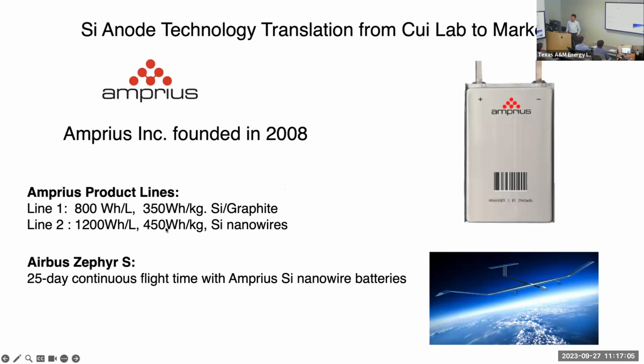Amprius is now delivering 450 watt-hours per kilogram product to the market, and we also have a silicon particle line that delivers 350 watt-hours per kilo. This is much higher energy density compared to the existing graphite technology. One of our high energy density batteries, we supply to Airbus, the Zephyr S, a commercial drone flying at very high elevation, about 60, 70,000 feet, continuously for 25 days without needing to come down to earth. They have a solar cell to charge it up during the day and store energy in our high energy density battery, and it flies most of the time relying on battery power. This requires very high energy density, and only Amprius can make it successful.